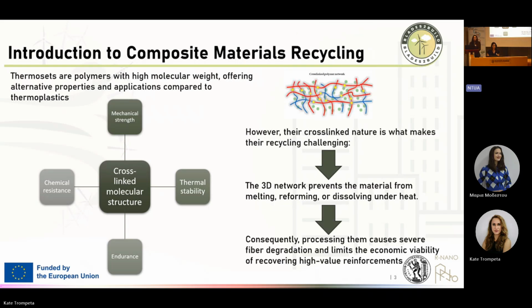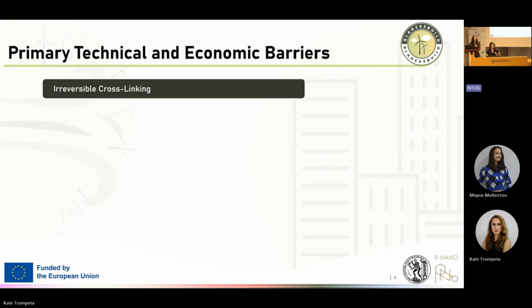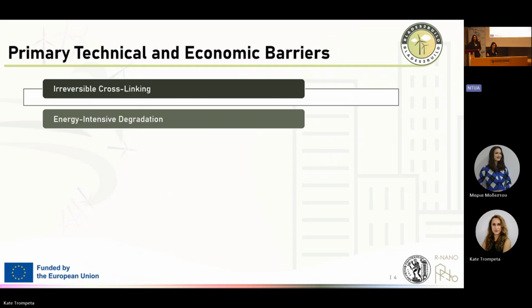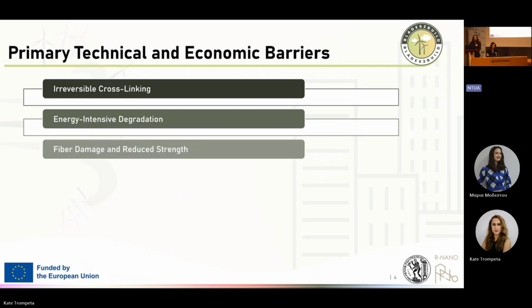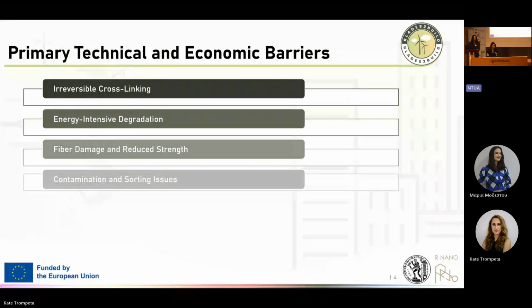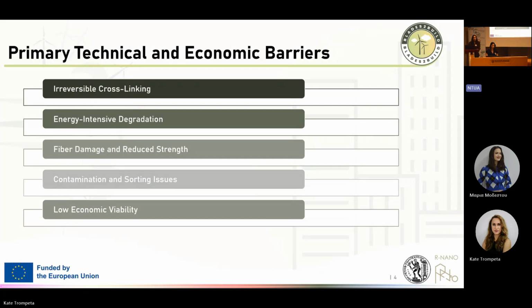However, this cross-linked nature is what makes the recycling challenging. The 3D network prevents the material from melting, reforming, or dissolving under heat. Consequently, processing causes severe fiber degradation and limits the economical viability of recovering the high-value reinforcement. So there are some technical and economic barriers that make recycling difficult, and that's why different recycling technologies have been invented, which will be presented next, in order to overcome these barriers that are related to the irreversible cross-linking, to energy-intensive degradation of the matrix, to the fiber damage and reduced strength that occurs after the recycling, the contamination and sorting issues that were also discussed previously, and the low economic viability of the current methodologies.